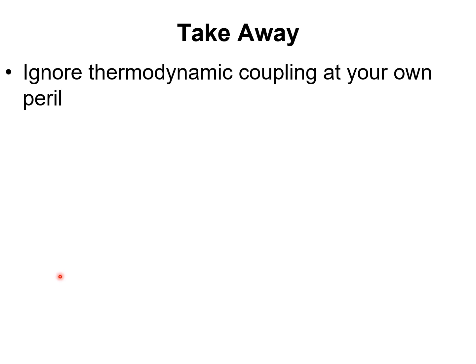And if we ignore thermodynamic coupling, no overshoots are realized. If you ignore thermodynamic coupling, the steady state fluxes are also not properly modeled.